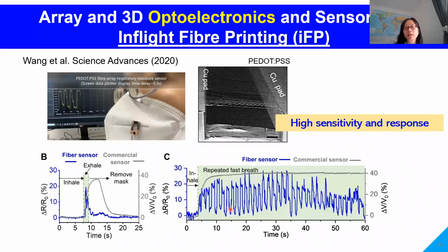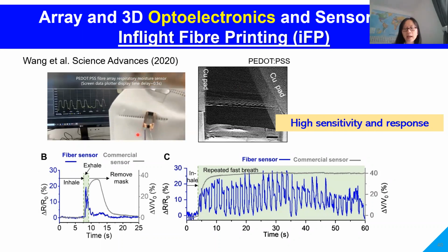To demonstrate the start of the proof of concept, what we did here is use IFP, which I introduced before, to create a sensing device. Here, we used PEDOT-PSS fibers because they are moisture sensitive. The PEDOT-PSS fibers are suspended on a frame, so you can't really see the fibers here because they are so small. And we used this device to measure the breath leakages from an N95 mask. Due to the small diameter and suspended nature of the fiber, we found that this sensor has at least 6 times better response than a commercial sensor.